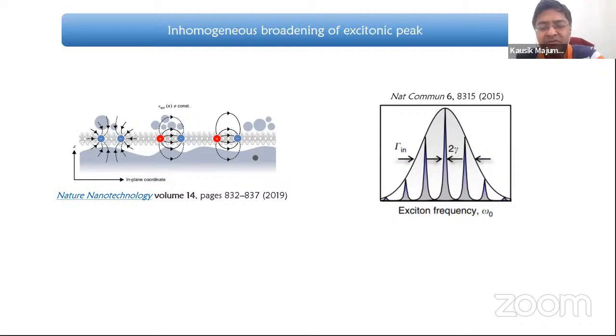No, so this is a phonon emission, right? You can always do phonon emission. This is not an absorption. So you are coming at a higher energy, and it can always emit even if you are at low temperature. That's not a problem, right? And it can come down to these kind of states. So we never see any such feature here. However, for the absorption part, yes, we do expect some bottlenecks like that, but not in the emission. Not in emission. Okay. Yeah, I have to cut down the discussion here.